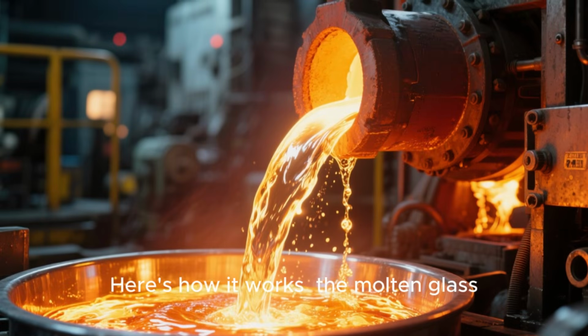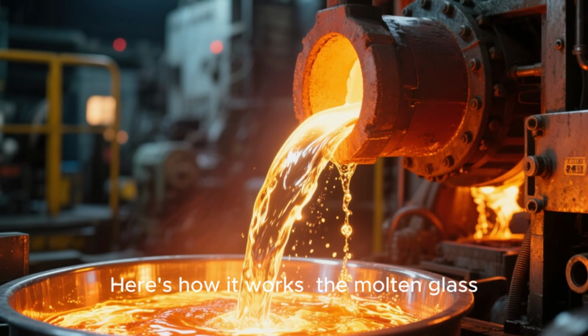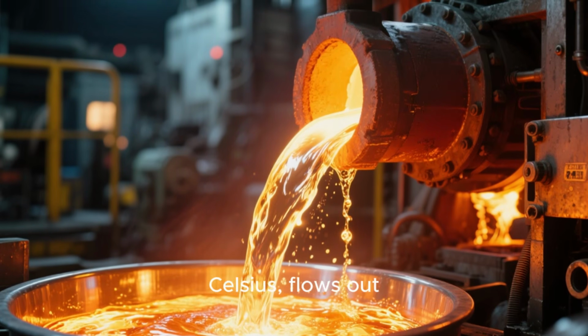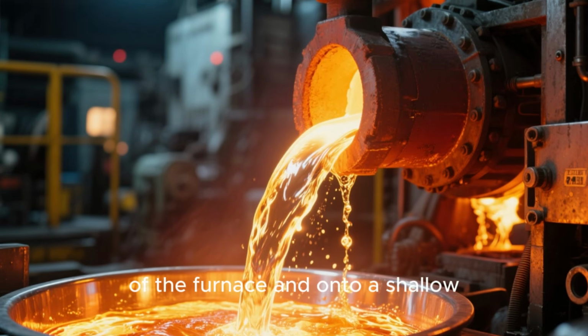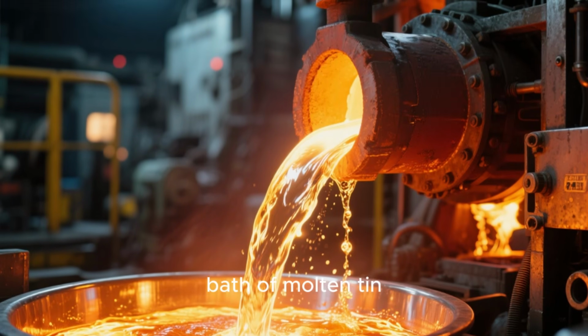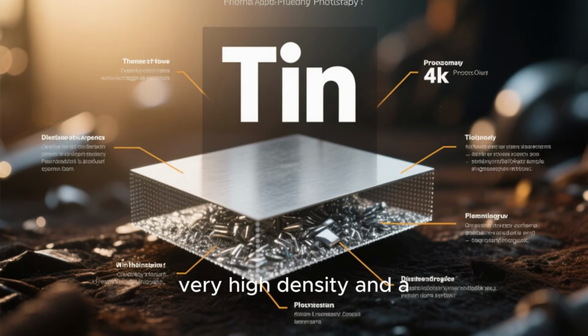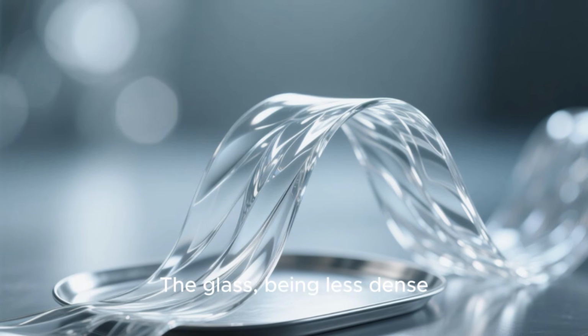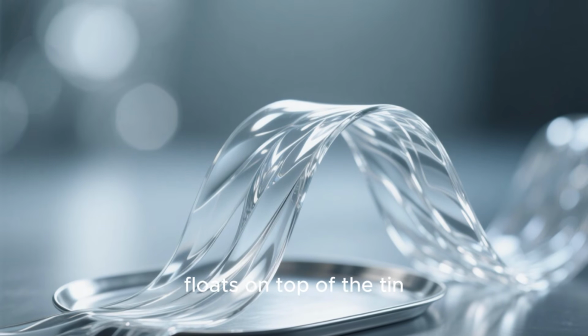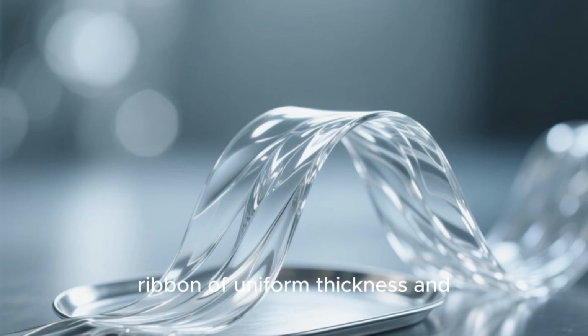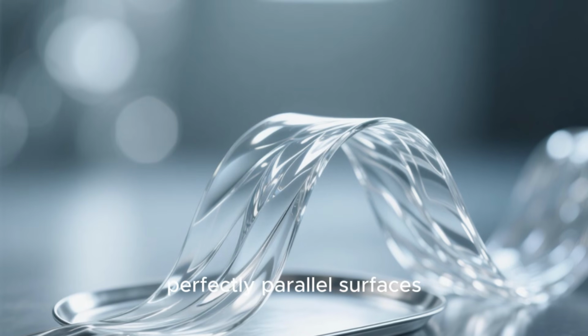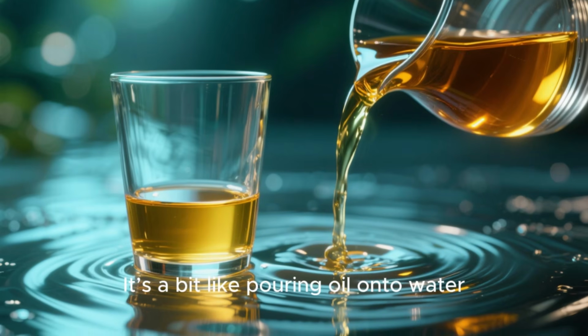Here's how it works. The molten glass, at a temperature of about 1100 degrees Celsius, flows out of the furnace and onto a shallow bath of molten tin. Why tin? Because tin has a very high density and a perfectly flat surface when molten. The glass, being less dense, floats on top of the tin, spreading out to form a ribbon of uniform thickness and perfectly parallel surfaces. It's a bit like pouring oil onto water.